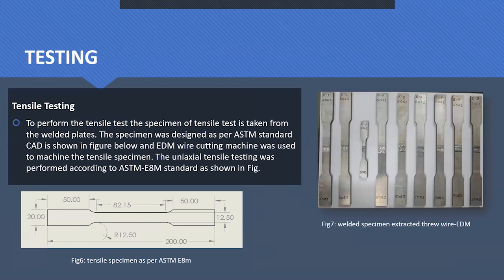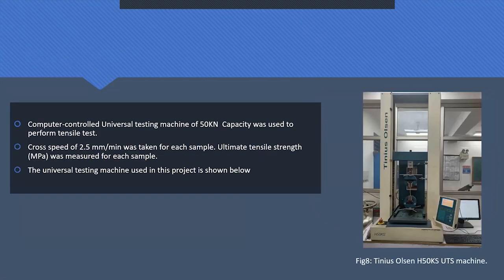So now we come to the testing part. For tensile testing, the specimen has been prepared in SolidWorks, whose design is shown in the figure below, and the standard is ASTM E8M, under which the specimen has been designed. The extraction of the specimen from the plates has been done using the EDM wire cut method. At the right, these are the nine specimens which were tensile tested. A universal testing machine with a capacity of 50 kilonewton and a crosshead speed of 2.5 mm per minute has been used for tensile testing of each sample.